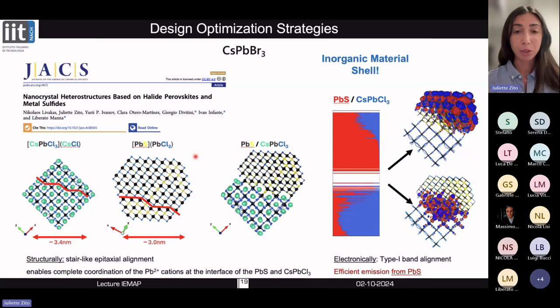What we can do from a computational point of view is to investigate again the structure and the electronic properties of these new materials. Structurally, we found that there is a stair-like epitaxial alignment between the two materials that completes the coordination of the lead atoms, both from the perovskite part and from the lead sulfide part. So basically, interfacing the two materials was healing the defects in both domains.